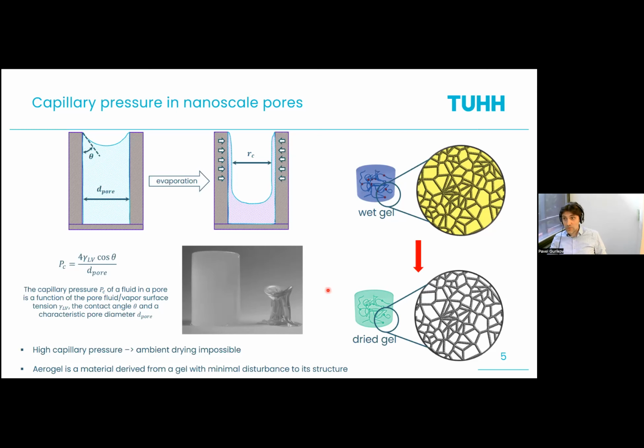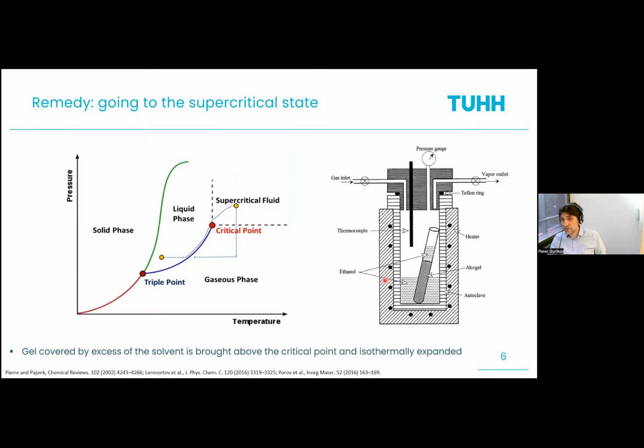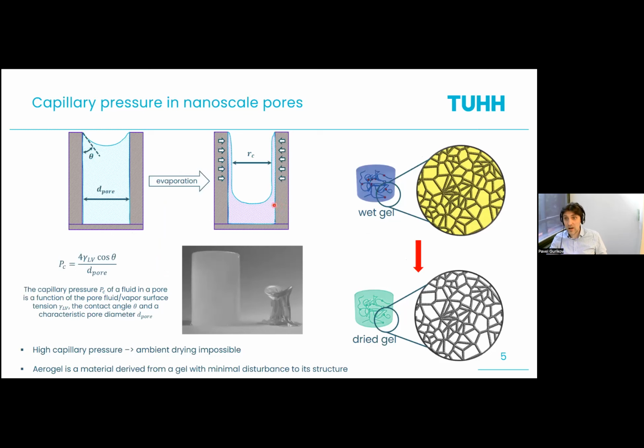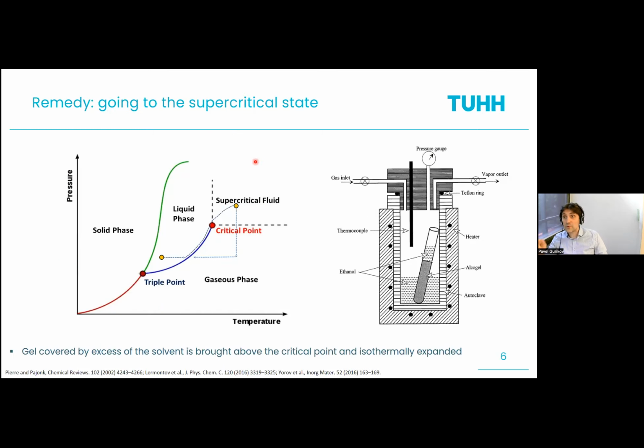What are we supposed to do with this? How do we bring the wet gel into a dried gel state? And the answer is, because we're in the high pressure section today, to use high pressure technology and use a very nice and very powerful fact that liquids and gases do coexist, but only in a limited range of pressures and temperatures. As soon as pressure and temperature exceed the so-called critical point, then you land in a place which is called the supercritical fluid region, where there is no difference between liquid and gas. If you slide back and take a look, I have liquid here and gas here. Indeed, if I bring this liquid into the supercritical state, then I don't have any capillary pressure anymore.